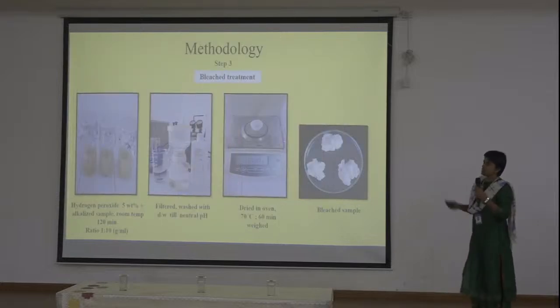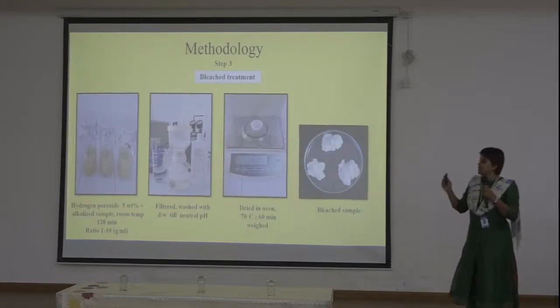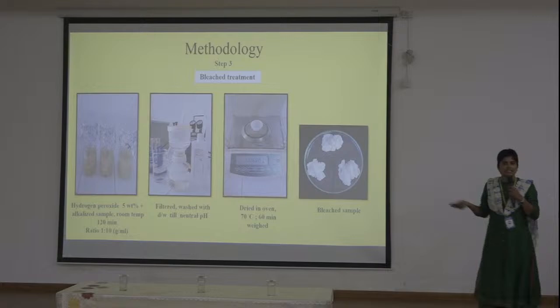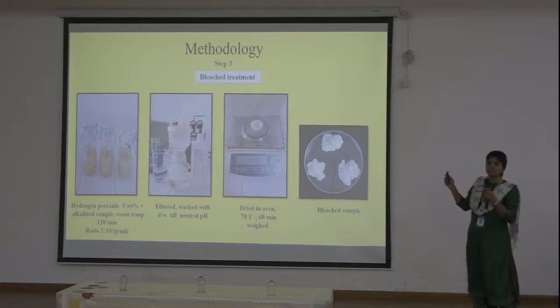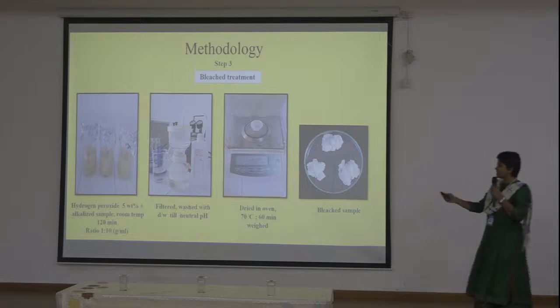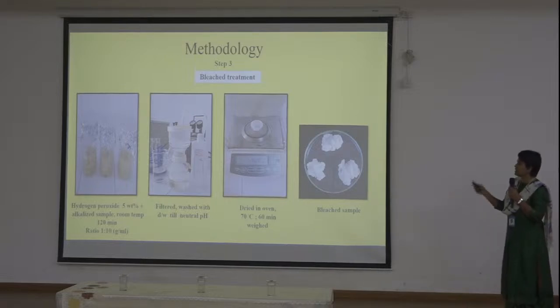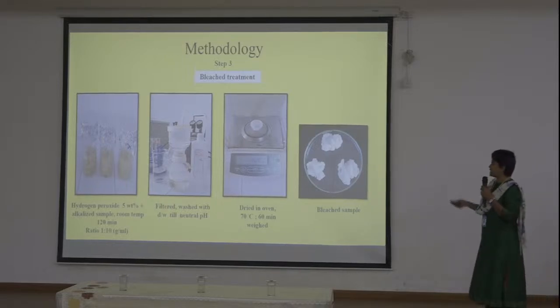Next is the bleaching step, done to remove lignin. Hydrogen peroxide is the classical method used for this. Here also the optimal temperature condition was optimized, and after the treatment it was washed, filtered, dried in the oven, and weighed for yield calculation.